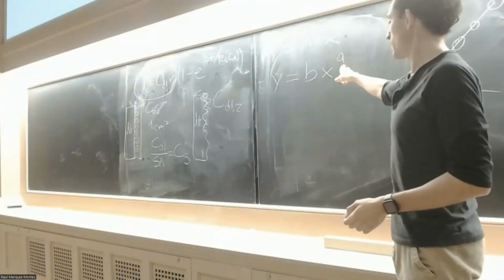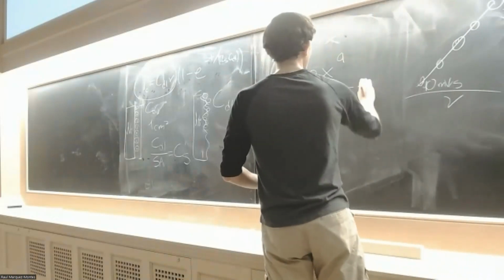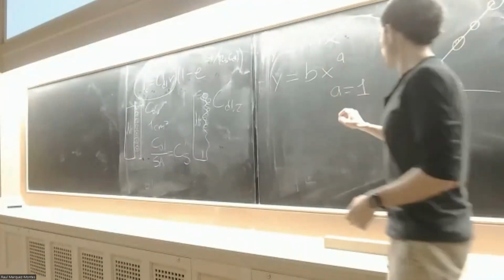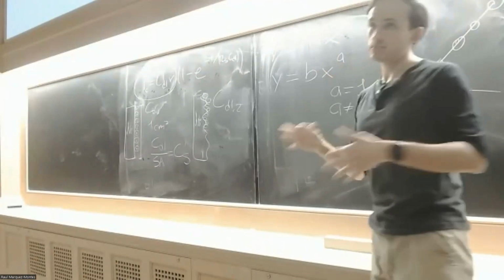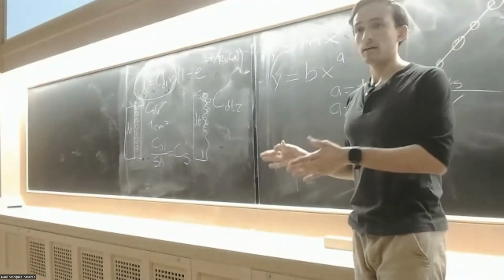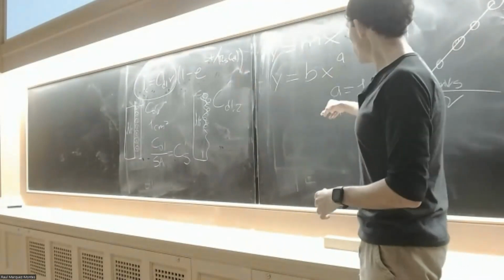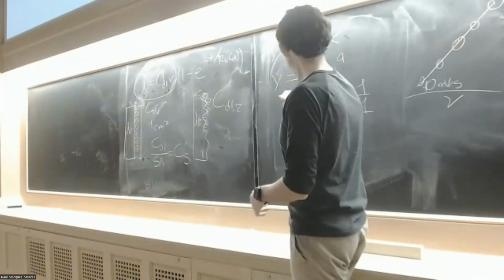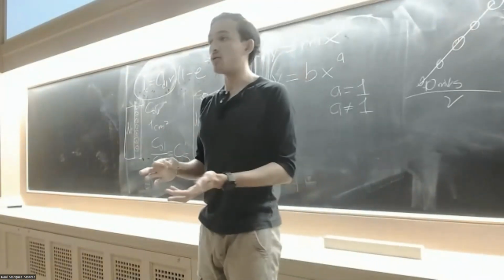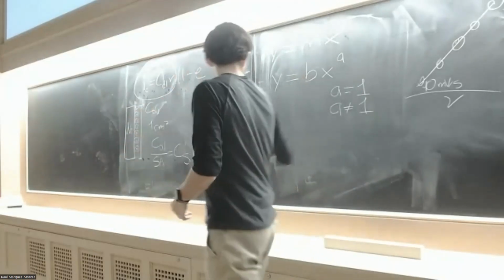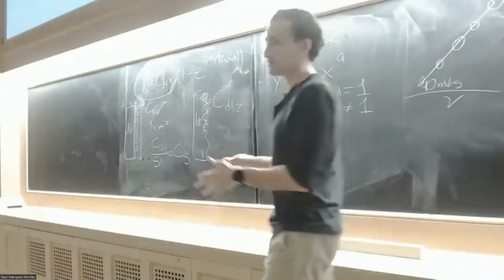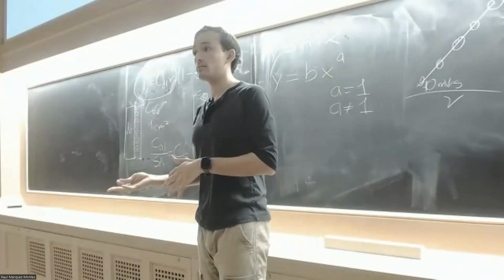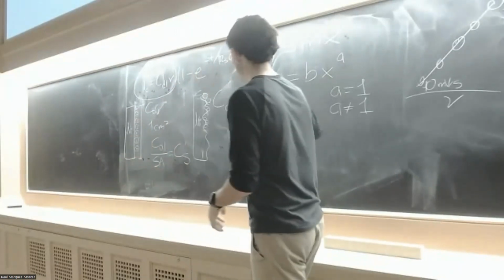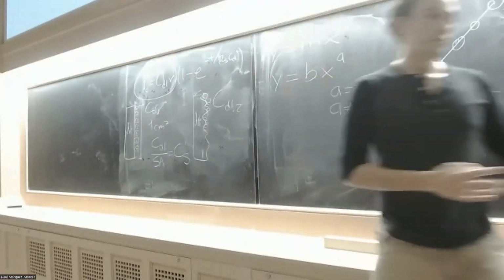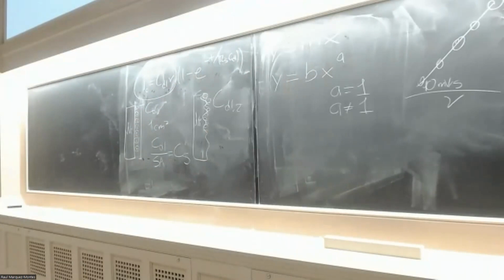Because this exponent here, if it equals 1, it's just basically this equation. But if it's smaller than 1, that means that we're deviating from the ideal behavior of the capacitor. So we want this value to be as close as possible to 1. If you use this fitting instead of this one, you can get an idea of how ideal your capacitor is. And if this value is, let's say, 0.8, maybe that means that the capacitor is deviating a lot, and therefore maybe it's not truly capacitive, or maybe you're not using the right potential window. Okay. So just to show you some final insights, let me share the screen with people in Zoom.